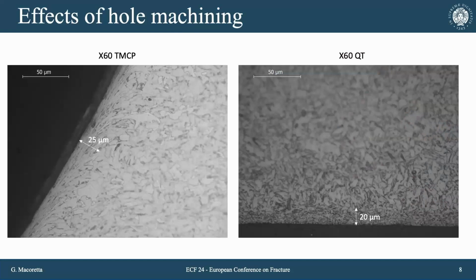If we also assess directly on the microstructure the effect of plastic deformation produced by the drilling and reaming process on the material, we can see that the drilling process affected a thickness of about 25 to 20 microns, both in the case of the X60 TMCP and the X60 quench and tempered material. You can see the difference, it's more evident in the first one because of the more ferrite grains.